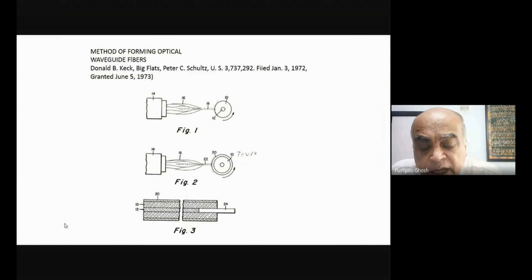Both of them. And that's how the pure silicon is made, from silicon tetrachloride. So it's interesting. And I hope you can understand the crucial intermediates, which has a bearing on fiber optics as well as on solar cells, that they all actually start with something like silicon tetrachloride. So what they were doing was making a mixture of silicon tetrachloride and titanium tetrachloride, which was taken in a way that the two will deposit in a very uniform way. So suppose I've got the inside tube, or it could be on the underside of the glass or on the outer side of the glass, depending on how exactly you're doing your work.